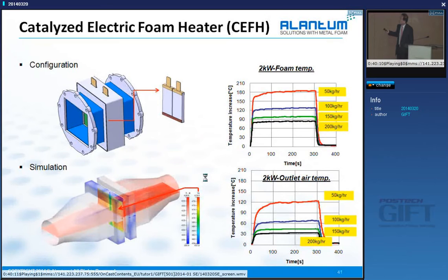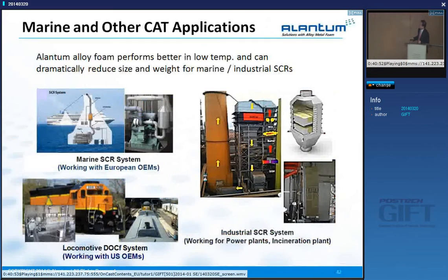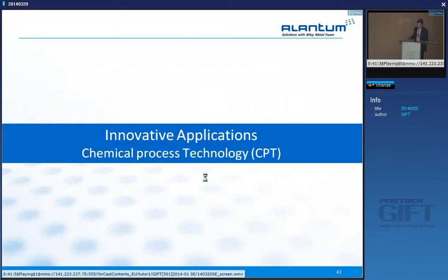With a low velocity, low flow rate, even with foam, we can raise the temperature about 180 degrees. But with air, we can only raise about 120. But no matter what, this flow rate is fairly low for reality. So once we are working in an automotive environment, maybe our temperature rise could be only 20, 30, or something like that, because there's a limitation of electricity. In an automobile you are using just a battery. A battery gives you only 1 or 2 kilowatts. That's the maximum, okay? So in addition to automotive, marine or locomotive, all these things we can do as transportation. So this covers the OCAT.